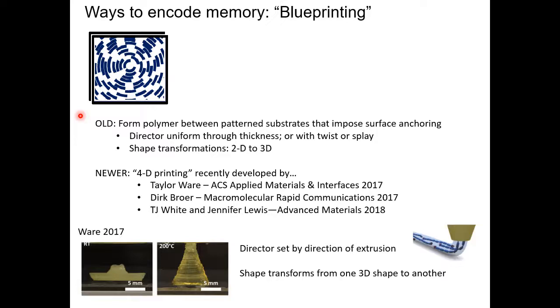And for a long time, like, I don't know, for 10 years or more, this was considered the best way to get some kind of imposed orientation. The easiest thing was to put the same orientation through the thickness. You could also, if you want to, put different patterns on the front and the back. Then the liquid crystal might be kind of confused and has to figure out what to do. It will, for instance, have a twist. Like I said, you can put a twist through the thickness, different kinds of things. But you just do the surface treatments and then put the material in between the two treated surfaces and hope for the best. There's a newer way to do it, which is what they call 4D printing.